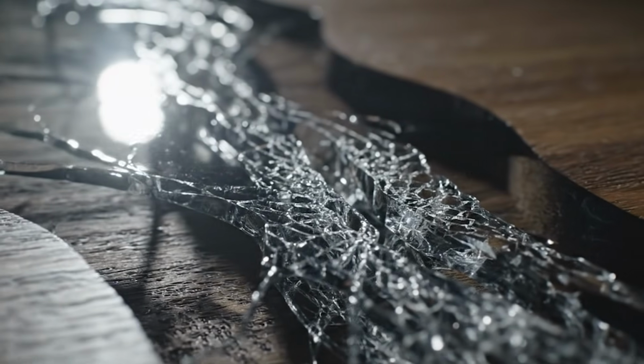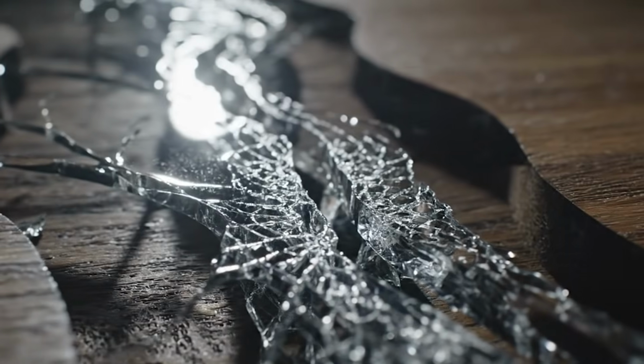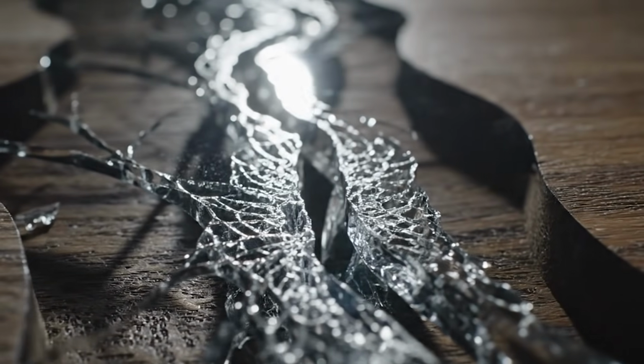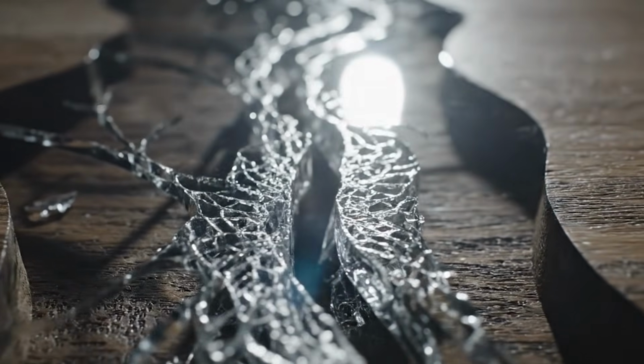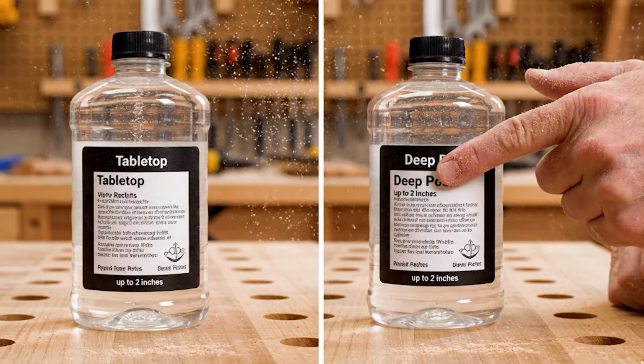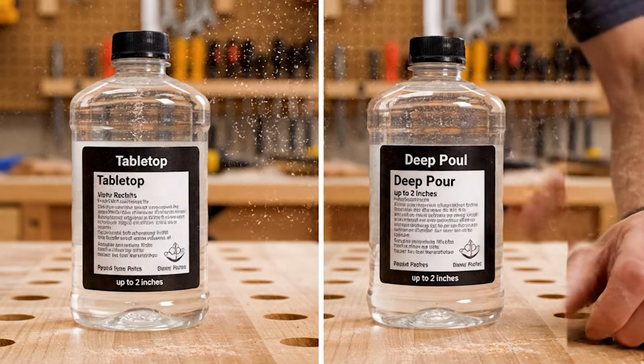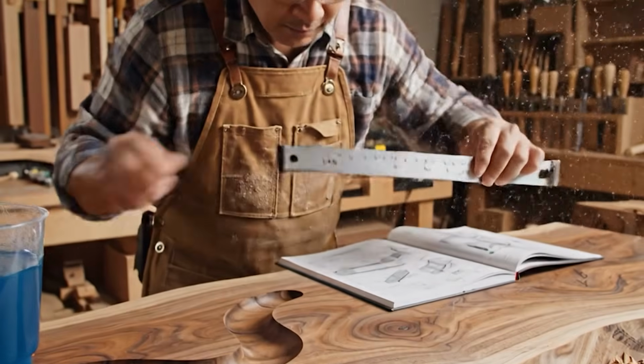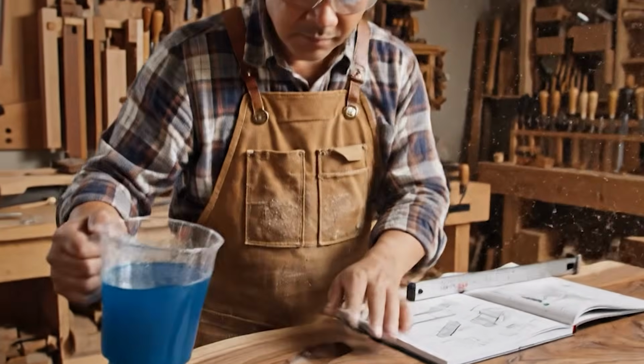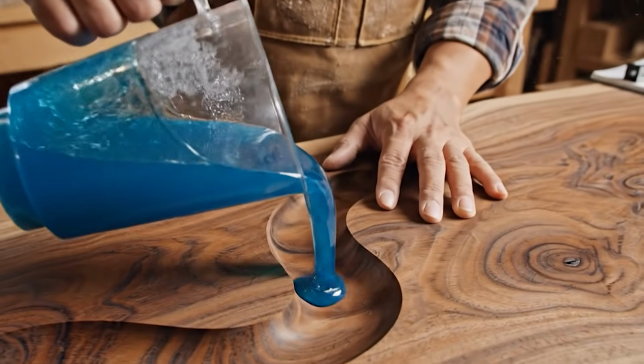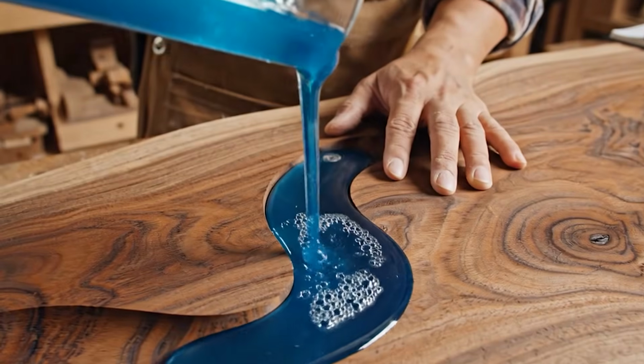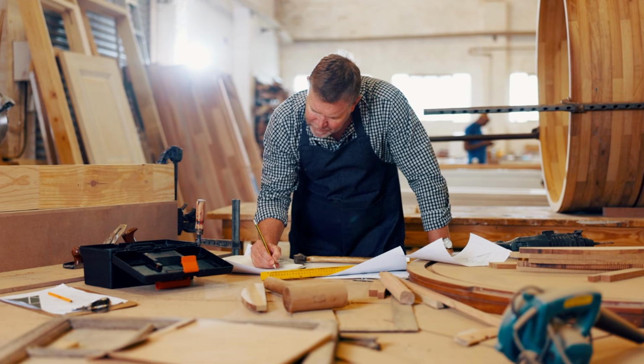Fifth, the epoxy cracked during curing. This is an exothermic reaction, meaning the resin generated too much heat. It happens when you pour too deep with a standard tabletop epoxy. Always use a deep pour formula for anything thicker than a 1/4 inch and follow the manufacturer's maximum pour depth recommendations. The good news is, if you follow the steps we've covered, you should be able to avoid most of these issues entirely.